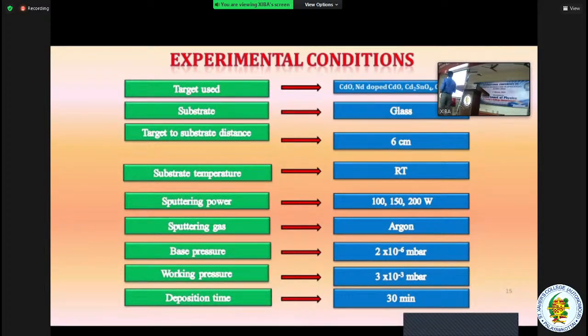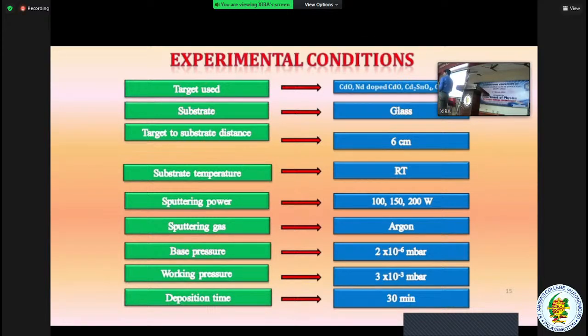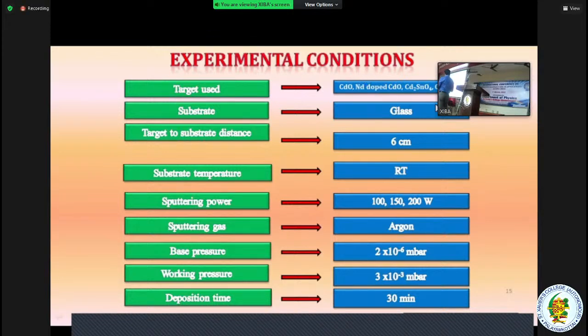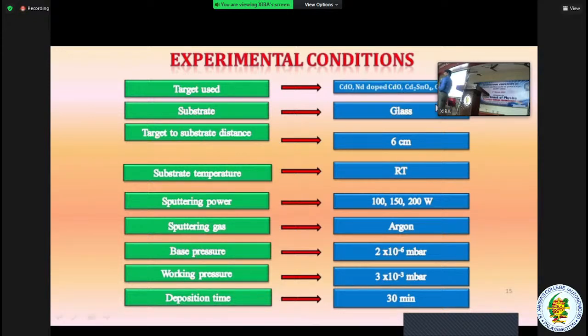So this is the experimental condition. These four materials we have used as the target, and the substrate was glass. The target to substrate distance was 6 centimeters. Substrate temperature was room temperature. We varied the sputtering power from 100 watt to 200 watt. Sputtering gas was argon, and the base pressure was 2 into 10 power minus 4 millibar. Working pressure was increased from the base pressure level to 3 into 10 power minus 3 millibar. The optimized deposition time was 30 minutes.